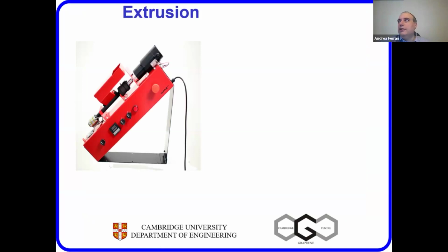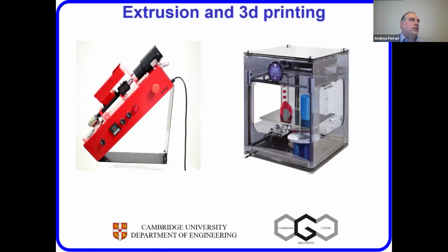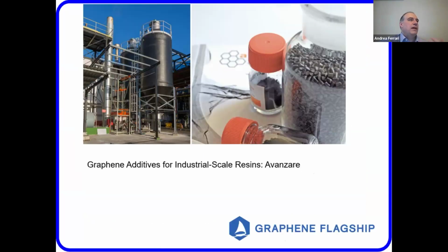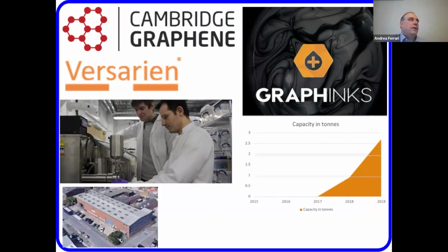With time, not only 2D printing but also 3D printing became interesting. We were able to do extrusion of filaments and then 3D printing of filaments. Within the graphene flagship, these composites were then developed, for example by Avanzare, which has set up a very large new factory in Spain, or in Cambridge by Cambridge Graphene, a company we founded that was then taken up by Versarien. You can see the capacity - many years ago when they started it was 0, and already by 2019 it was several tons per year. That's the facility where they started doing the production.